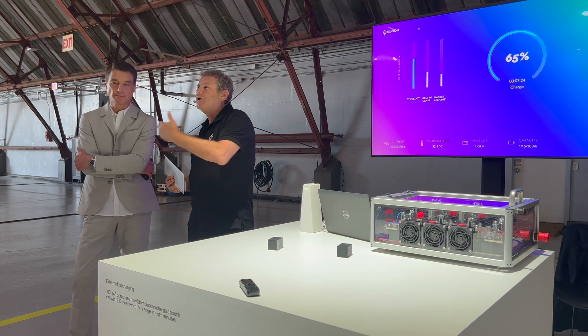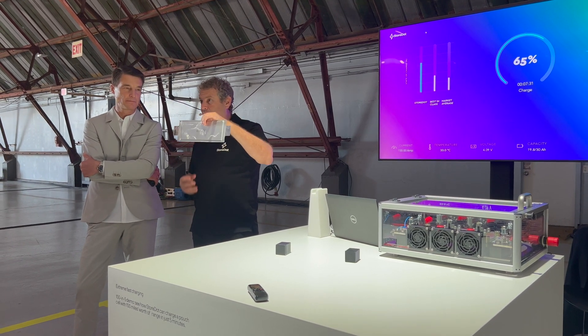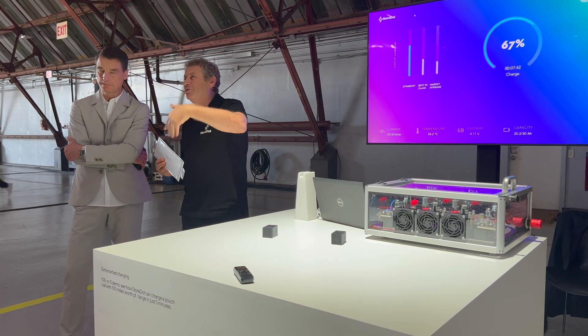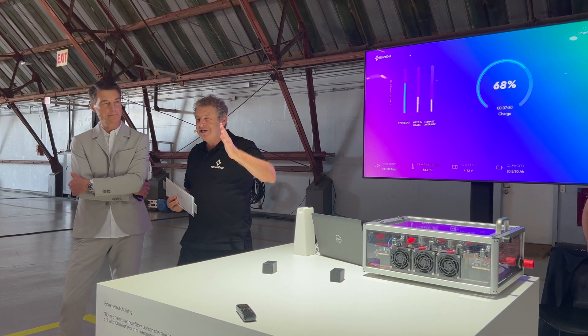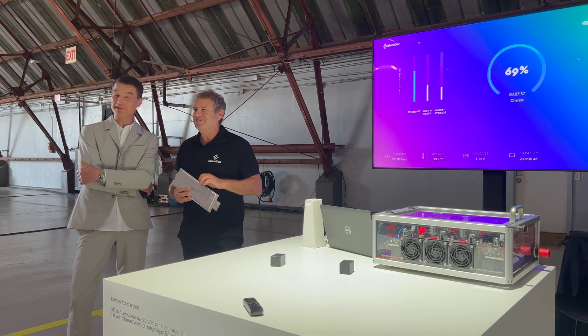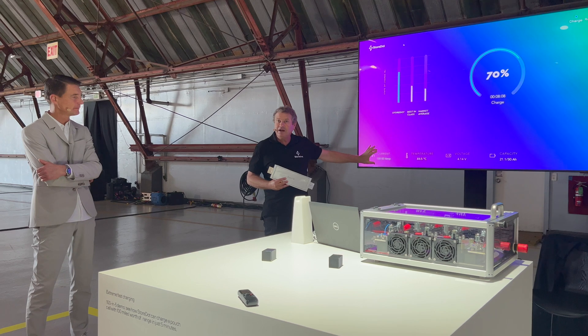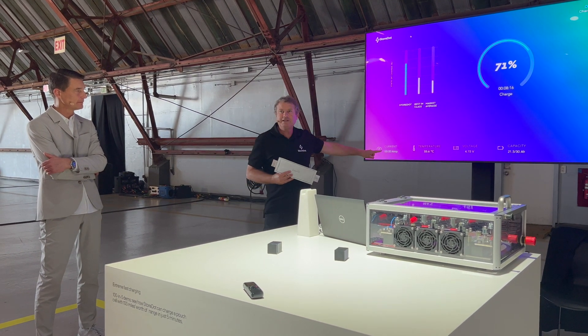This is not five or ten years away — it's happening today. These cells are produced in China by our partner, who is also our investor. We've already produced tens of thousands of these to produce the vehicles — and we're producing more than one vehicle, though we'll only demonstrate one. This is already in production on traditional lines and we haven't changed anything in that process. Eight minutes have passed and we are at 69–70 percent. The constant current is still at 135 amps — if this were a graphite battery you couldn't keep this up for more than a minute.